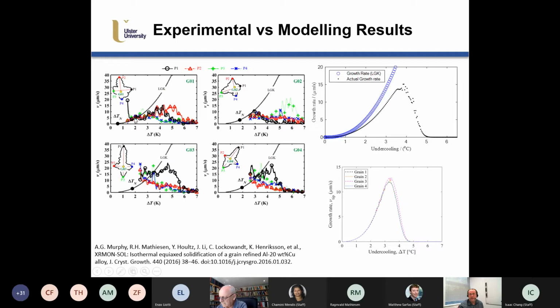Looking at LGK growth, and looking at the actual growth measured from measuring 4 directions on select dendrites, you can see that it doesn't really live up to the LGK growth, and that's because of impingement. And comparing that then to the model results, our model is driven by LGK growth, but that drives the extended volume. It doesn't drive the real growth. And the back calculation of the radius allowed us then to calculate the real growth rate after impingement.